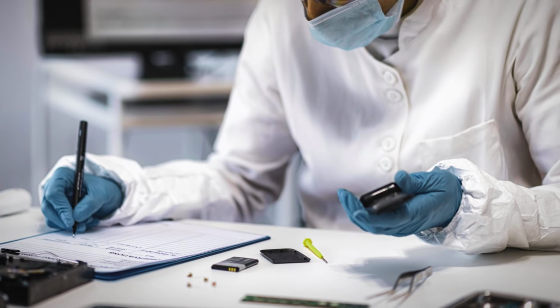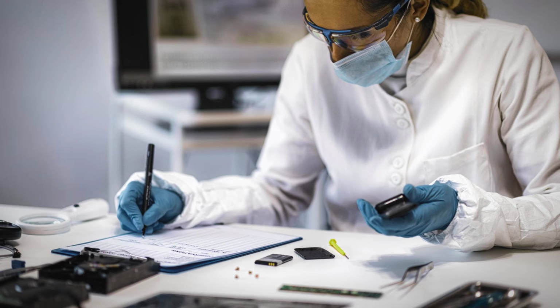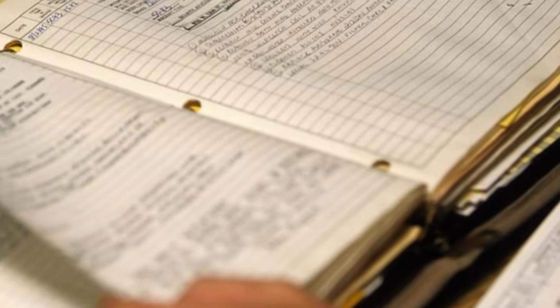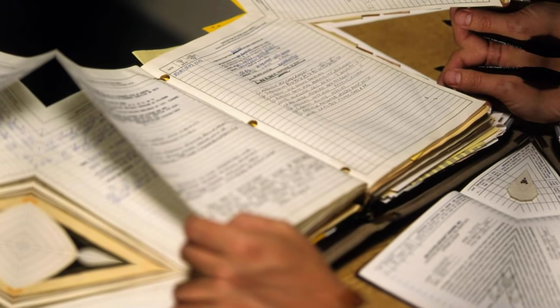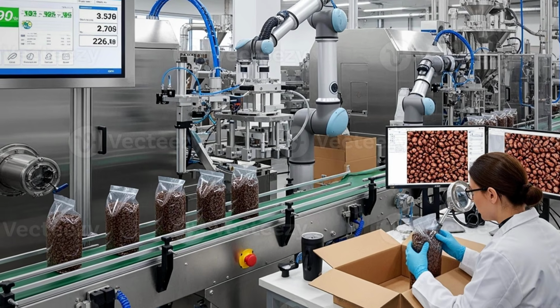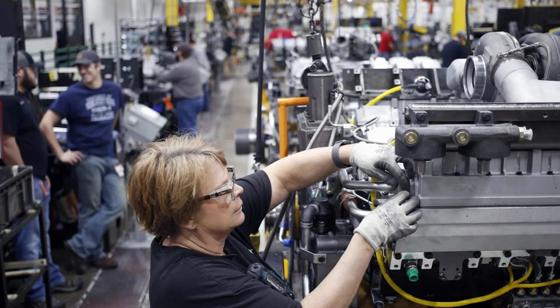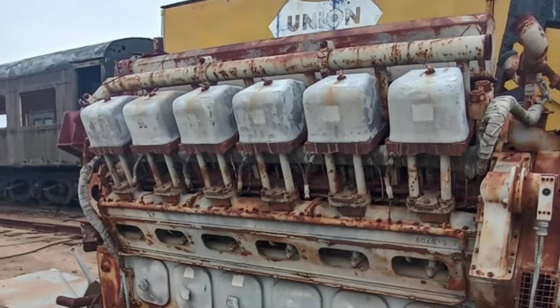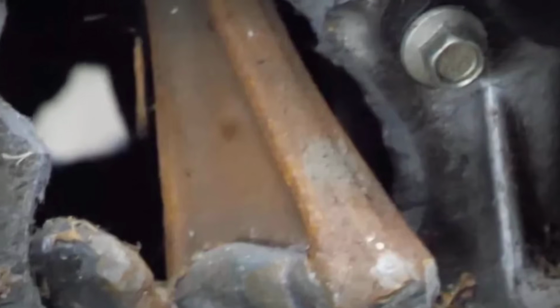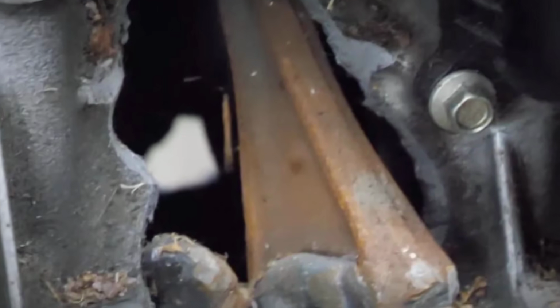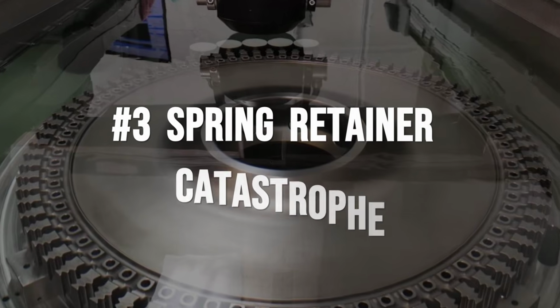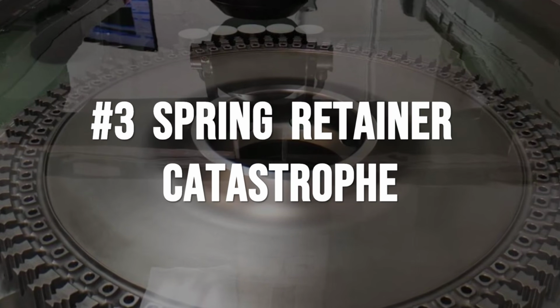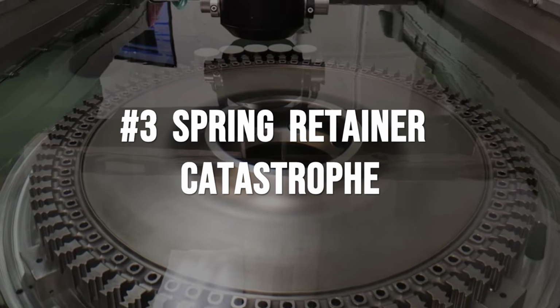The metallurgist's conclusion is explicit: failure initiated at the inclusion site with no prior evidence in the service record. This is not a random accident. It is a manufacturing defect, undetectable in the field, that transforms a flawless prime mover into a $2 million wreck. The mathematics are final. The violence is absolute. Coming to the top 3, the spring retainer material substitution is a crime written in procurement records and metallurgical cross-sections.